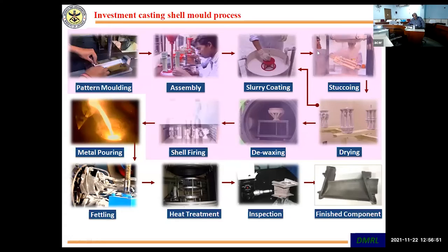Here I'm just showing you the investment casting process. You first make the pattern molding, then assembly, then carry out the wax pattern you make, then slurry coat. You build up different layers of the slurry coating, then dry the shell mold, then pour the metal, and then break the shell mold, and then do different kinds of inspection to make an investment casting part.